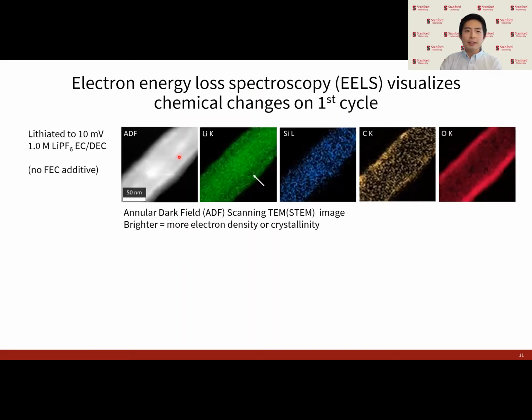So this dark field image down here shows strongly scattering regions in the core coming from the lithium silicide, along with a dense oxide layer, and then a lower density surface layer. Lithium intensity is strongest in the lithium silicide core, with a dip in intensity in the lithium silicate layer due to the low lithium concentration in lithium silicate, and then another enrichment in the SEI layer. The electrolyte reduction is also reflected in the carbon signals on the outer surface coming from the organic carbonates, and then the oxygen is enriched on the outer surface due to the lithium silicates along with the organic carbonates.